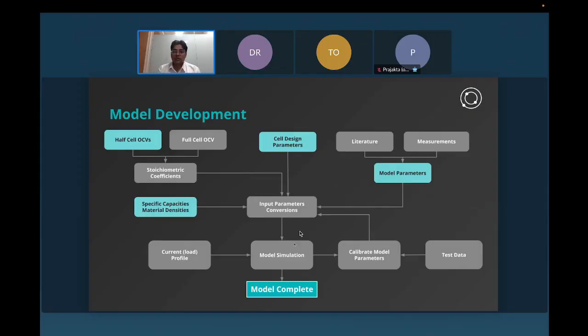Now, from whatever processes Dr. Raghu described, and from all of those equations, the overall model development process involves, first of all, knowing the half cell OCVs of each electrode, and you have the full cell OCV, which you can get from cell testing, either by doing a slow discharge process, and based on this you first calibrate the stoichiometrics. And then you have these cell design and material parameters that are input to us, and these can be available either from the cell suppliers or one has to do the teardown. And the problem that we are focusing on here is the model parameters, and these need to be known to collectively take all of these input parameters and put them into that set of equations to get a voltage response.